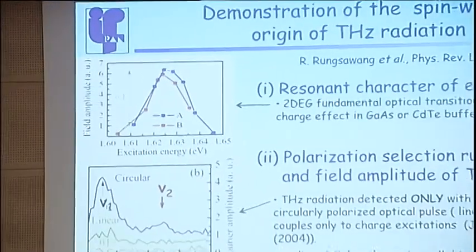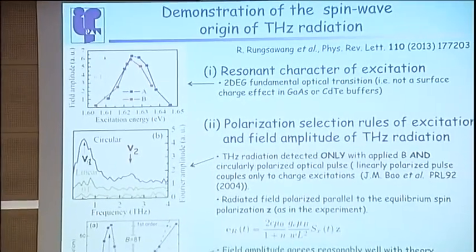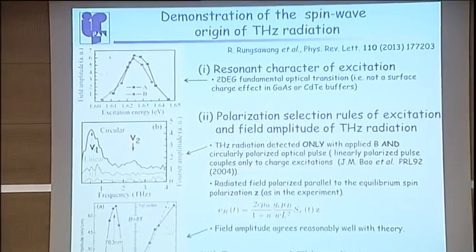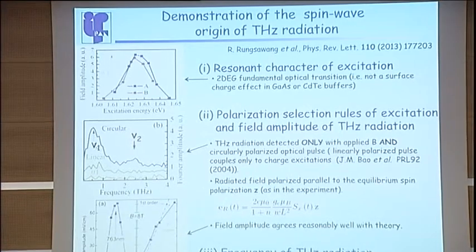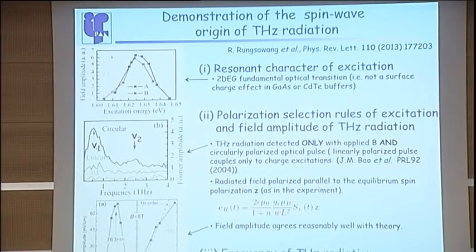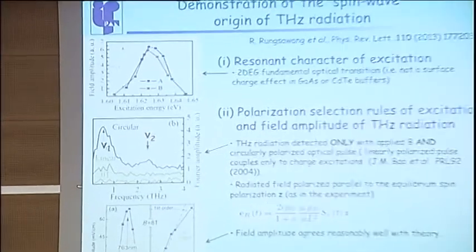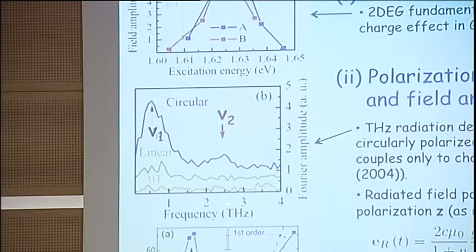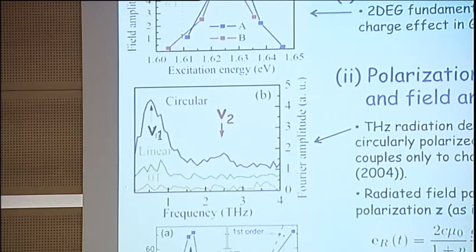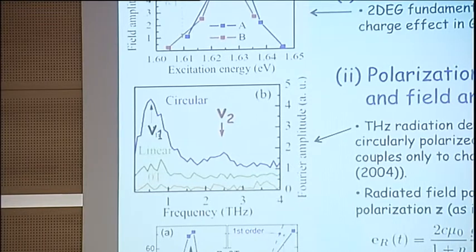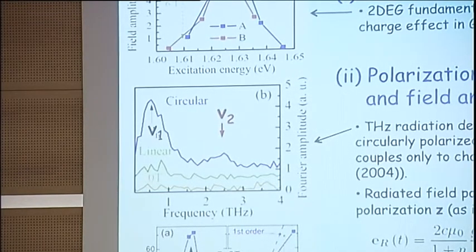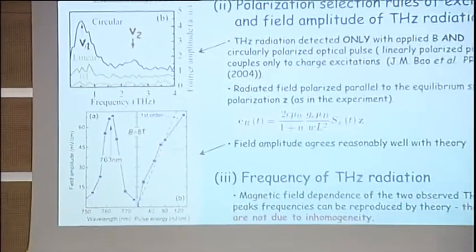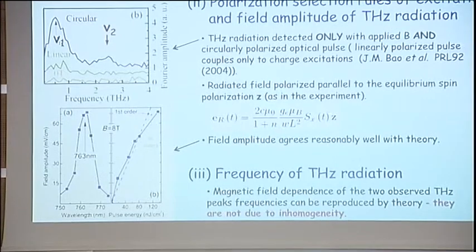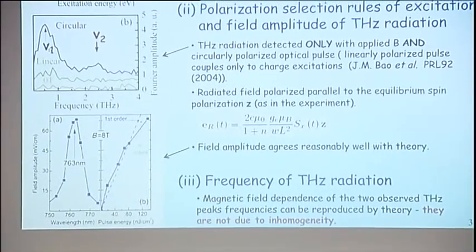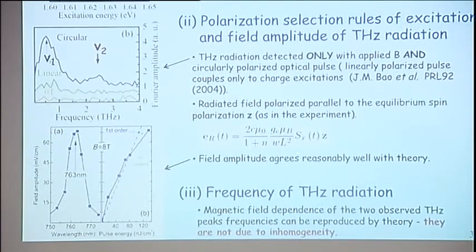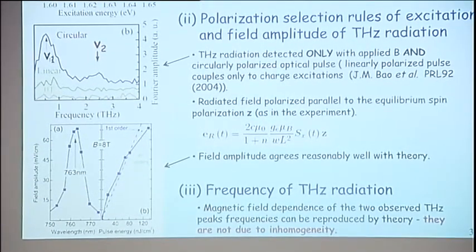Now, in order to show the spin wave origin, one can use polarization selection rules, and it has been demonstrated by our colleagues that at zero magnetic field, where you don't have spin polarization, you do not observe those terahertz pulses. With linear polarization you do not observe it because it can only couple to charge excitation, and you can only observe it in the presence of circular polarized light. Also the radiated field has an electrical field along the z-axis, as we have set the detection system. And the amplitude also reasonably well agrees with the theory.